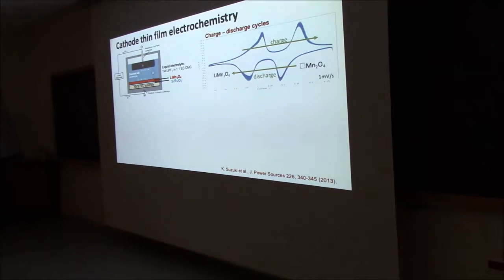Why is the discharge cycle a little more decreasing than the charging in the lower one? A lot more decreasing. You mean the peak here? The left one, the peak. This one. Yeah. Why is the peak so much decreasing in size? Yeah. So what you see here is at which voltages, if you scan through this, reactions are happening. And this is different than when you have a structure where no lithium is in and is moving to specific spots, or when you have it fully, you take them out, because the connectivity of this material is different than when it's fully lithiated or not.